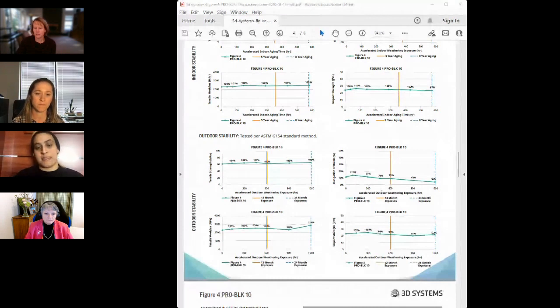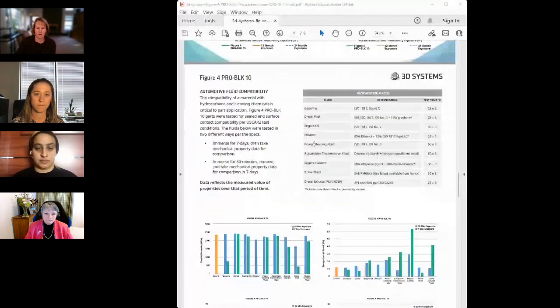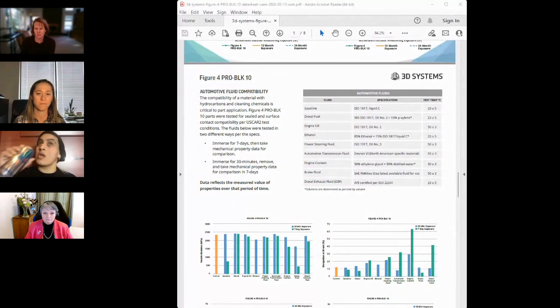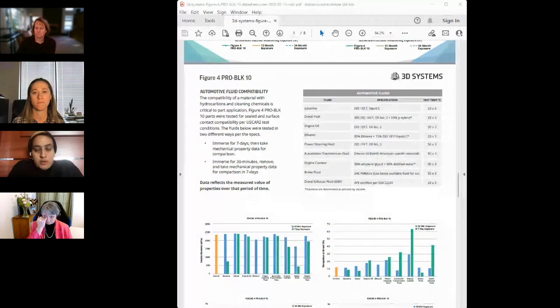And then the last section I'll go over is our fluid compatibility testing. And that is, we actually do 2 sets of fluids. We do the automotive fluids, which is what I have shown here. That's based on the US car standard. And then we also do some other fluids like solvents and water-based systems like acids and bases, which is an ASTM standard. But the basic concept is you expose the printed object to this liquid, and then you measure its properties at different times to see how they might have changed with the exposure.